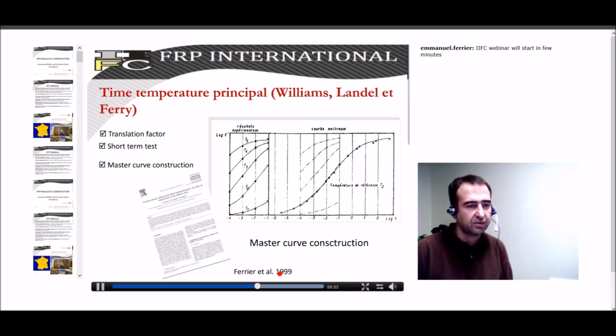Then the second issue, which is interesting to focus on, is the creep issue. This was part of my work done during my thesis also. At that time, we were interested in getting the full master curve of an adhesive using the time-temperature principle, basically based on the Williams, Landel and Ferry hypothesis that it's possible to get the full creeping relation using short-term tests with different temperatures. The idea here is you have, during a short period, a temperature giving you a creeping curve. If you increase the temperature, you will accelerate the creeping, and then the creep will increase. And when you increase the temperature again, you can get several curves.